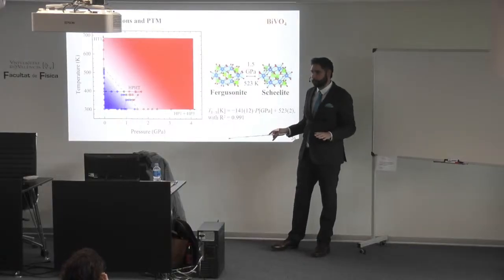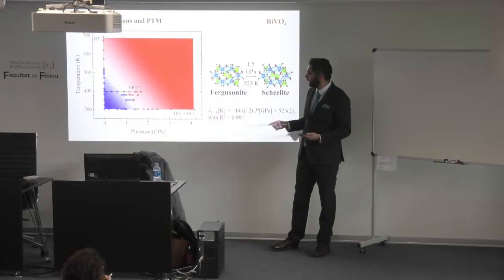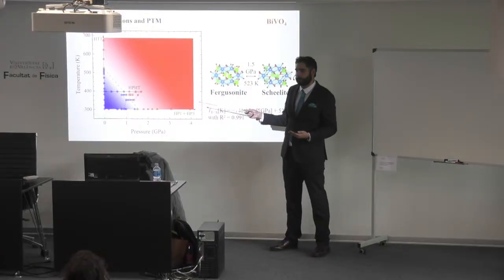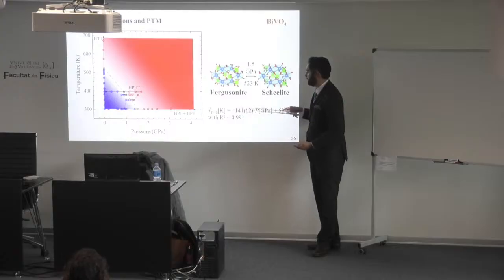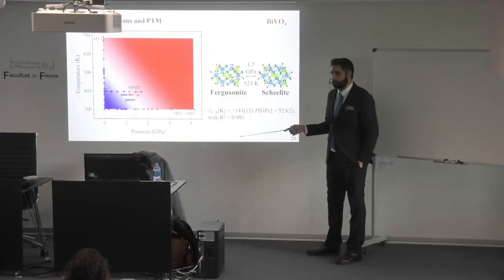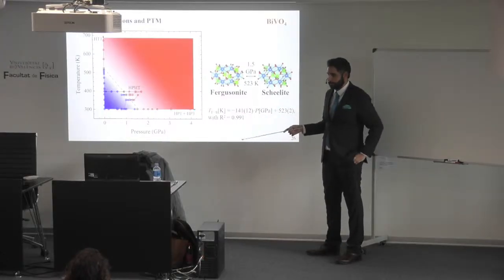In this case, we can clearly see that this phase transition has no hysteresis. The second order behavior is related to it in a way that it has no hysteresis. And this is the result that was also published in other papers, so it is compatible with it.